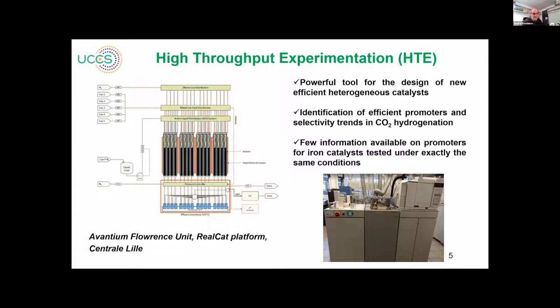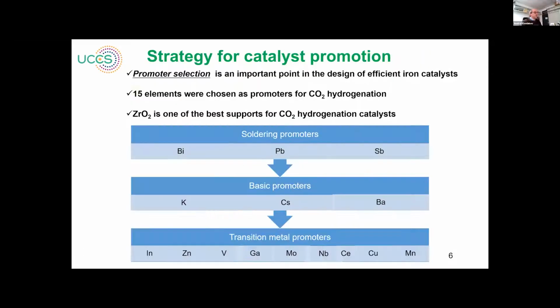And of course, we cannot compare which promoter is the best, because we can only compare the things that can be compared. However, for that reason, we can test in our setup a large number of catalysts. We know how they were prepared, and we can test them in the same conditions of activation and catalytic reaction. So this is the strategy which has been used for this work.